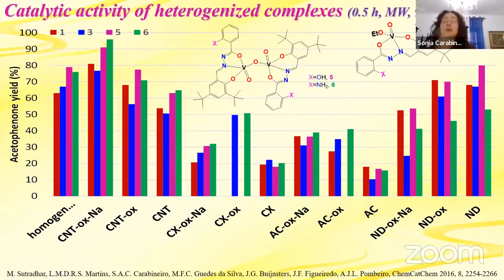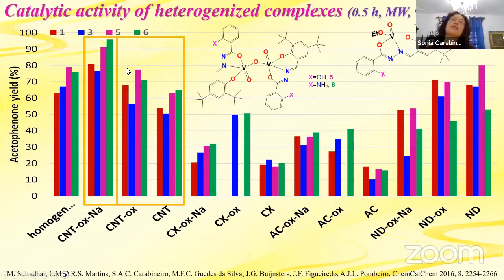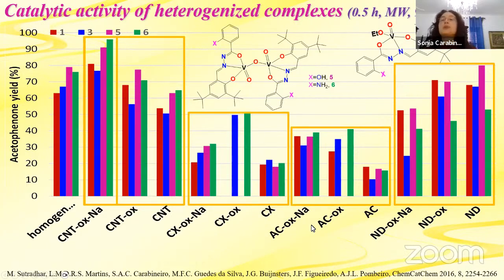And here we have the other complexes that could be anchored on all carbon materials. Those two complexes only on nanodiamonds. They were very, very selective. So we see here the best results with carbon nanotubes oxidized with sodium hydroxide, as expected. In general, the best results were obtained with carbon nanotubes, but here we have the homogeneous one, and only this one was better. And of course the nanodiamonds were also good, and these ones were worse.